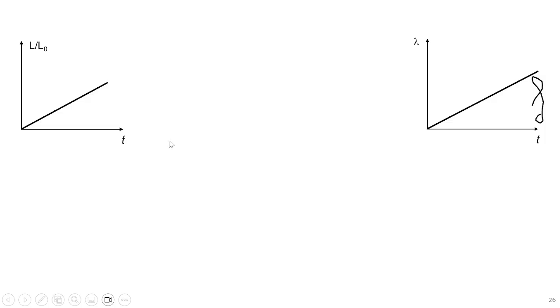And the explanation is the same. You stretch. If you do a so-called delayed rupture, which usually means you stretch very fast and hold it. After you stretch it, you hold it. There's no further deformation. Nothing further going on. This is the most beautiful experiment because there's no ongoing deformation. And then if you wait enough time, he waited as long as 7 days if you don't stretch enough. He's a patient man. So it could be seconds, could be 7 days, depending on how much you stretch and hold, and depending on temperature as well.